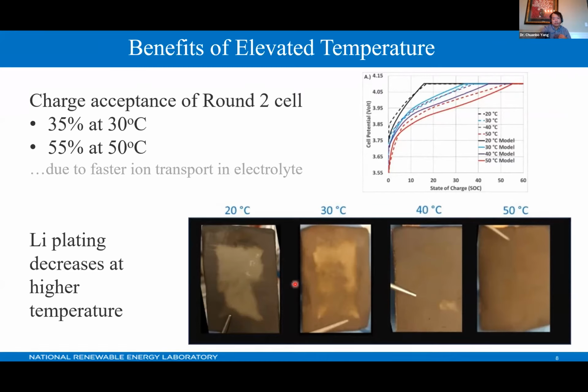The bottom figure illustrates the lithium plating condition after we open the cells. A large amount of lithium can be observed. A shiny silver area can be seen at 20 and 30 degrees Celsius. Conversely, very little lithium plating is visibly detected for cells operated at 40 and 50 degrees Celsius.